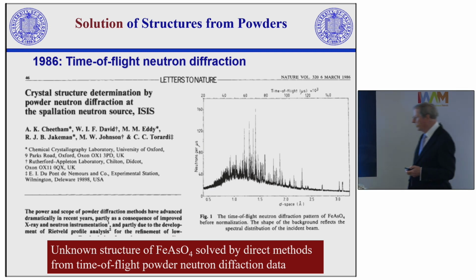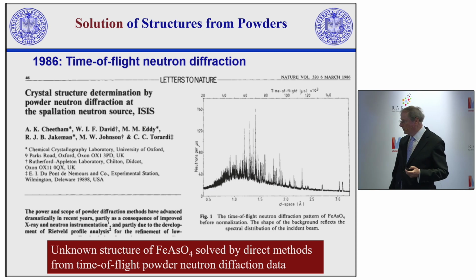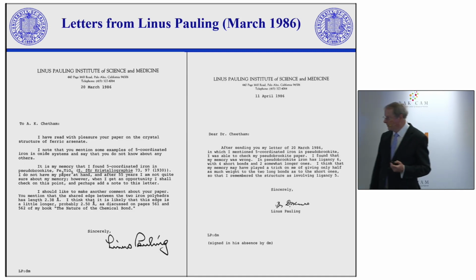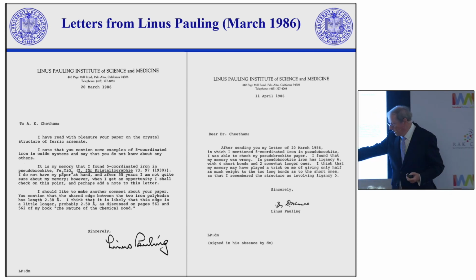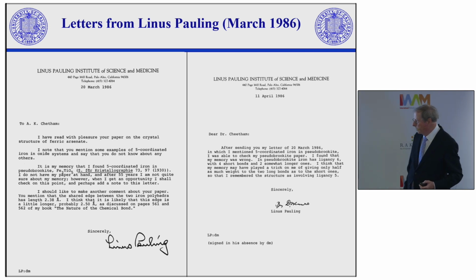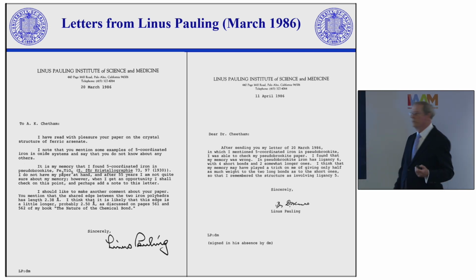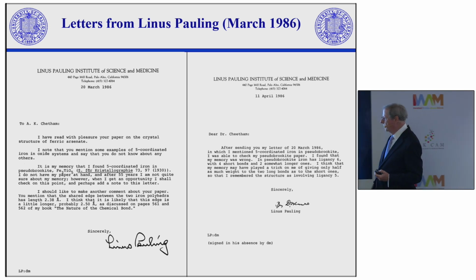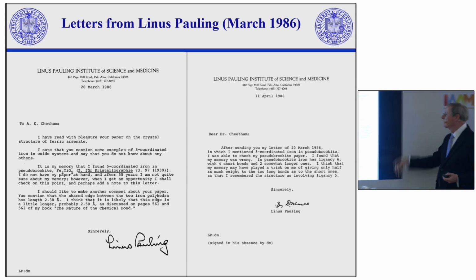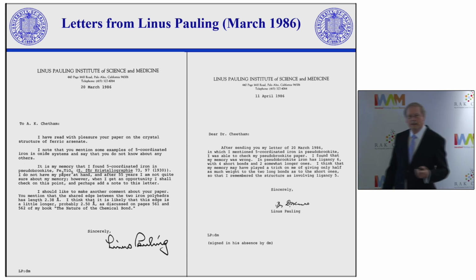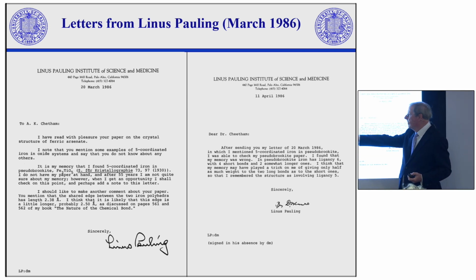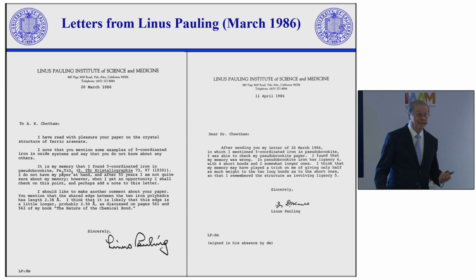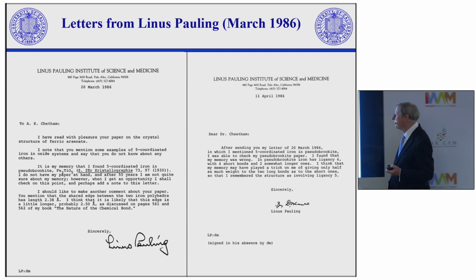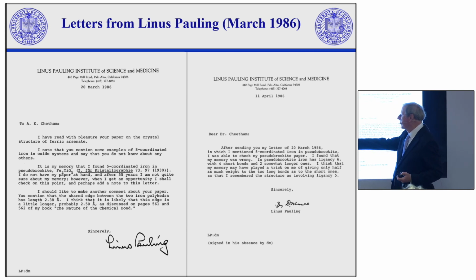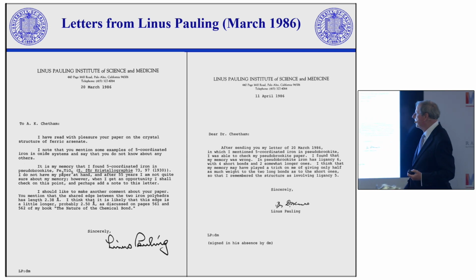So this is just a short segue. We chose this iron arsenate, which was of unknown structure at the time. The reason I wanted to show you this is that this caught the attention of Linus Pauling. And Linus Pauling wrote to me, and it starts off very well. I've read with great pleasure your paper on the crystal structure of ferric arsenate. And then he says, you mentioned some examples of five-coordinated iron in the oxide structure. Then he gets to the point. If my memory's correct, I actually found five-coordinated iron in 1930, and you didn't cite me, is what he's saying. And he said, I'm not absolutely sure. However, when I get an opportunity, I'll check this point and perhaps send another note.